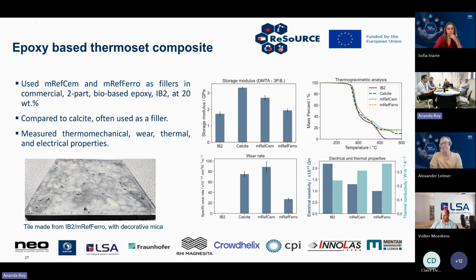Thermogravimetric analysis shows there's much more thermostability with the addition of these fillers. But looking into things like wear rate is quite exciting to see that the epoxy on its own doesn't wear a lot, but with the inclusion of calcite and MREF, a lot more wear happens, but then MREF-Ferro withstands that wear within the system. And then, as my fellow colleague Jack also mentioned about the different thermal and electrical properties, you can see that it follows the same sort of properties as we did observe with the initial raw materials in itself.